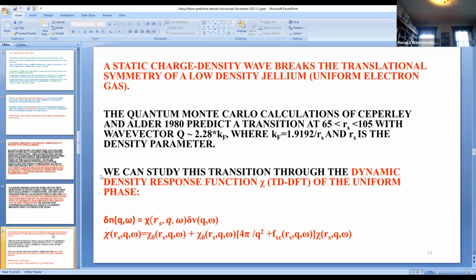And if you go to very low density, it's known that the electron density crinkles up in a so-called static charge density wave. Overhauser predicted this a long time ago. Later, it was found for jellium in the quantum Monte Carlo calculations by Ceperley and Alder in 1980. They predicted that this transition to a charge density wave occurs at low densities in which RS is between 65 and 105.